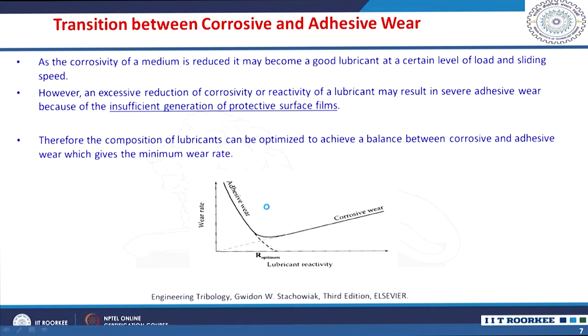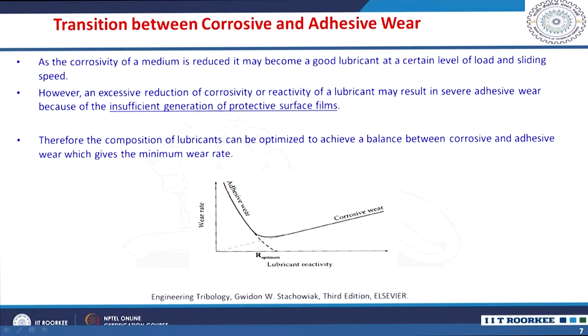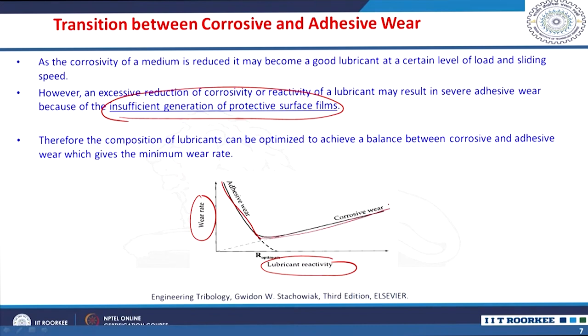As the corrosivity of the medium is reduced, it may become a good lubricant at a certain level of loading and sliding speed. However, an excessive reduction of the corrosivity or reactivity of a lubricant may result in severe adhesive wear, because of the insufficient generation of protective surface films. So, you can see the wear rate versus the lubricant reactivity. Adhesive wear is dominant up to this point, and then corrosive wear is dominant. So, there is a certain reactivity optimum where you can have both adhesive and corrosive wear at minimum levels. The composition of the lubricant has to be optimized to achieve such a balance between corrosive wear and adhesive wear, which gives the minimum wear rate.